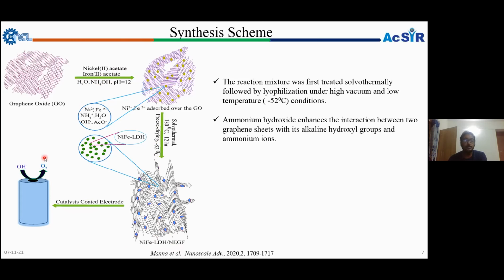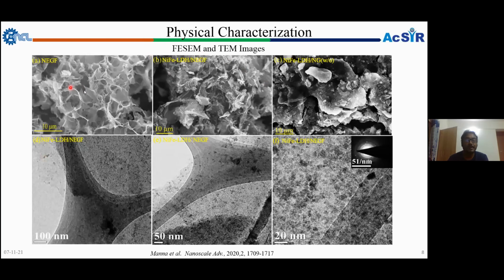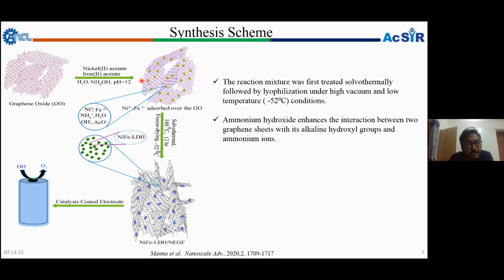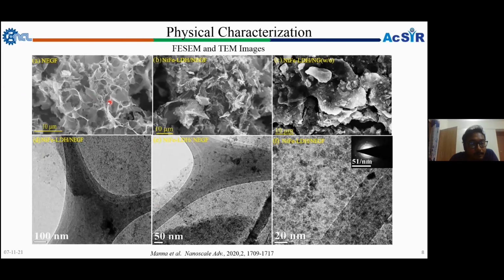To know whether the structure is formed, we have done various physical characterizations like FESEM and TEM images. FESEM is in the micrometer range. We can analyze the structure of the graphene sheet, because graphene has micrometer scale structure. So here we first checked the nitrogen doped entangled graphene to know the exact morphology formed for the 3D graphene. Here you can see, by applying the freeze drying method without any metal substrate added, the morphology is formed, that entangled structure we predicted schematically, and the individual sheets are connected through an angle, and the uniform porosities are there.